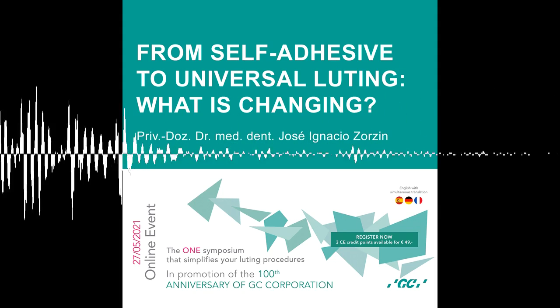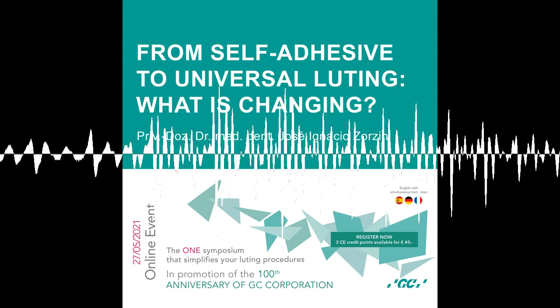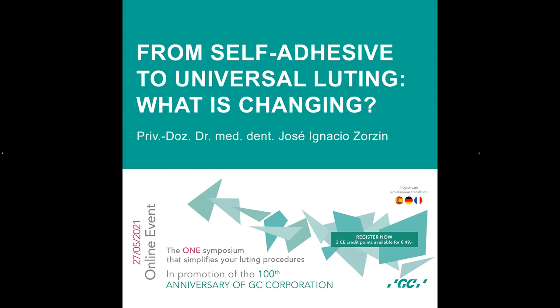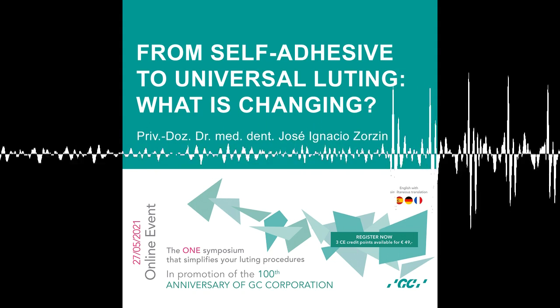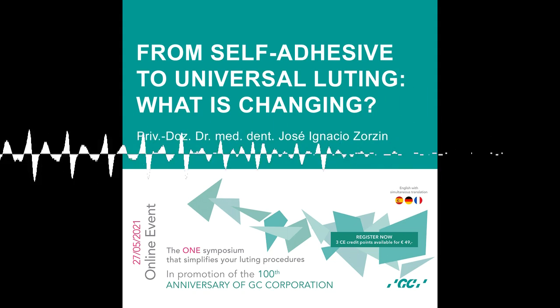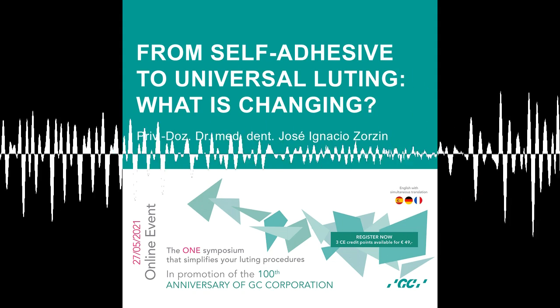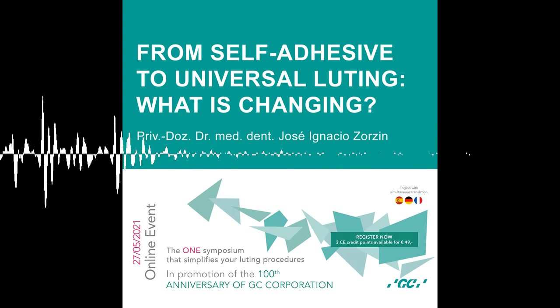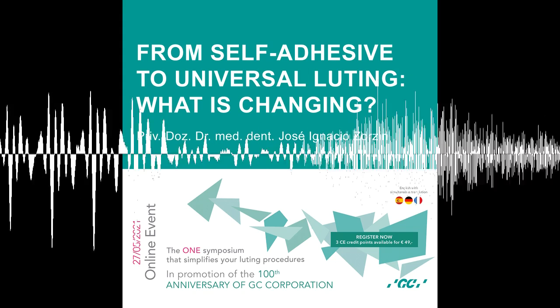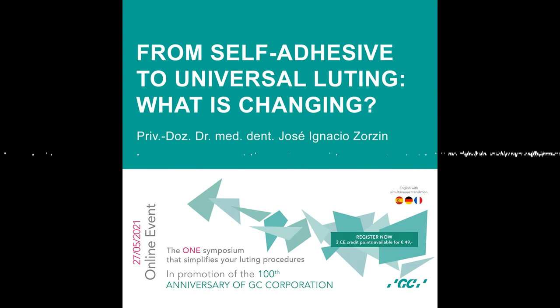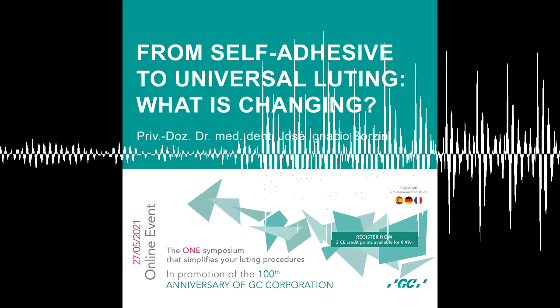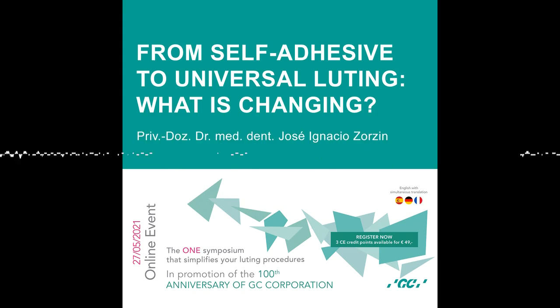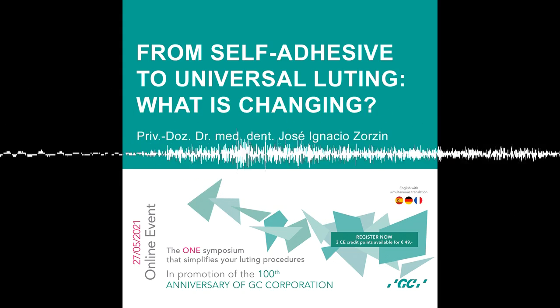On the chair side, most of the materials suggest 60 seconds. Look at silanes for dental technicians. They go for longer times, like 5 minutes. And there are interesting studies where they leave the silane 60 minutes in an oven, and then they get amazing adhesion results. But well, this is clinically not practicable. Now, imagine 60 minutes in an oven. I never heard of it. Yeah, I have to look for the exact literature, but there are some people doing it for 60 minutes.